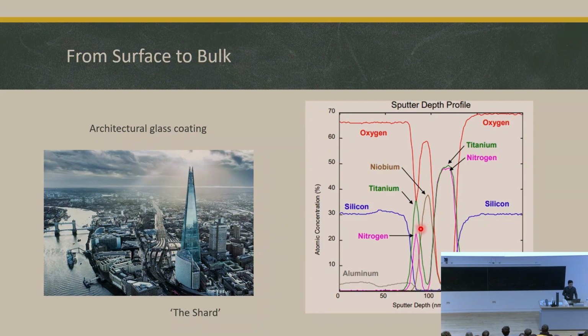Moving to about 100 nanometers beneath the surface, there's only titanium and niobium left. So this is niobium oxide, with niobium and oxygen left. The niobium oxide is a good humidity barrier coating for the glass. It has a high resistance to electrochemical corrosion. Then another layer of titanium nitride. And finally, after 150 nanometers beneath the surface, we see the normal glass, which is silica. So although it's very thin, and we can't even imagine if it is scratched, everything would be gone, it has applications for each of the components.